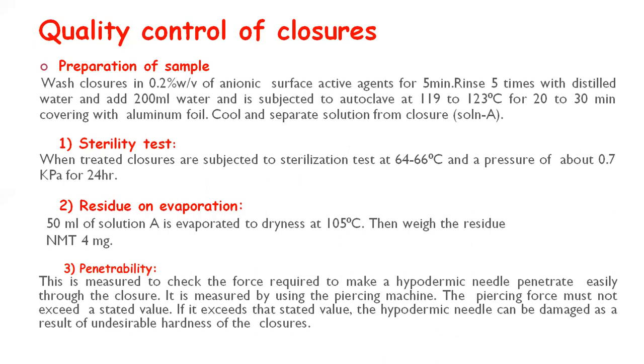Penetrability. This is measured to check the force required to make a hypodermic needle penetrate easily through the closure. It is measured by using the piercing machine. The piercing force must not exceed a stated value. If it exceeds that stated value, the hypodermic needle can be damaged as a result of undesirable hardness of the closures.